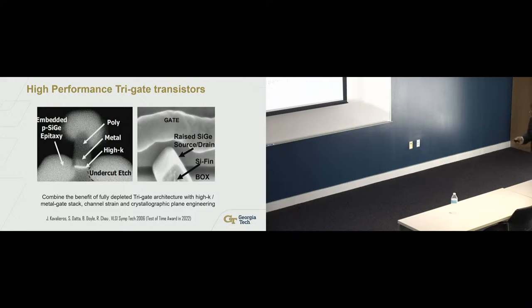There was a lot of work that happened at that point of time. You need probably the best etch engineers you can get your hands on just to create these fins with a sidewall roughness less than 5 angstrom. Anything more than 5 angstrom of surface roughness will create scattering. I'm talking about angstrom, not nanometer. And that will pretty much kill your transistor drive current. So that problem was solved.